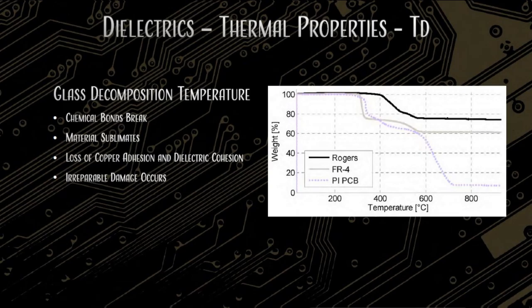You do get a little bit of damage in the multiple lamination cycles. There's always a little bit of damage. That's why you can only let some of these materials be laminated a certain number of times. So it can be irreparable, but that doesn't mean that it's a deal breaker, right? You can still potentially work with the board at that point. But these temperatures are Celsius, so these are really high temperatures. Yeah. Sometimes just getting it to flow is good for us when we're laminating, and this is like you've just destroyed the board. Yeah. And it's telling you at what point it will do that. So anyways, that's your decomposition temperature, your Td.